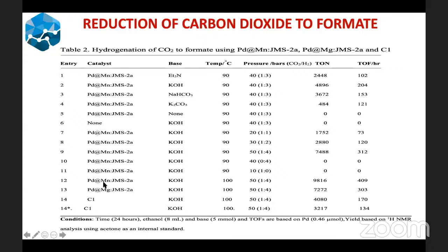Interestingly, these two MOFs, your magnesium and your manganese MOF, both contain the palladium complex, or palladium two sites, in the MOF. The magnesium one shows a lower activity. You can see under the same conditions, the magnesium shows a turnover number of 7,272 as compared to 9,816. This might be attributed to a number of factors. So you would need to go into different programs to analyze the channels, the size of the channels. Of course, these MOFs are isostructural, but a closer look at their structural features shows that there are some minor differences in terms of the pore size, which could have played a role in the yield that is observed here.